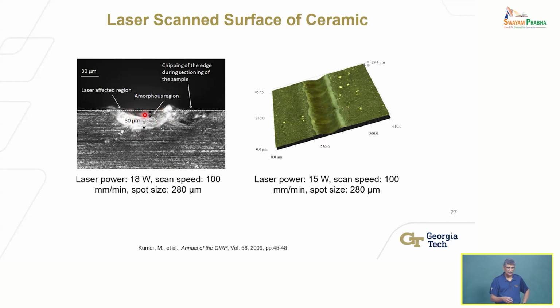So essentially, what is a sintered ceramic? Particles have been bonded together with heat and pressure. So you just basically disaggregated these particles, so it becomes amorphous, like powder. Powder is amorphous, right? So that's really what has happened here. And you can see that indeed there is also some ablation. You can see there's already a groove that has formed of some sort, right? Some of it is because this amorphized powder can fall off, because it's already weak. I don't even need to grind it, okay?